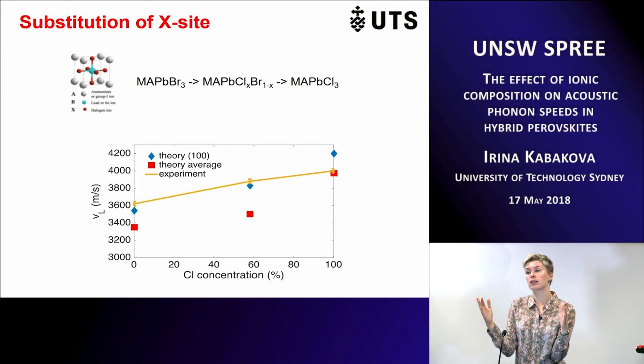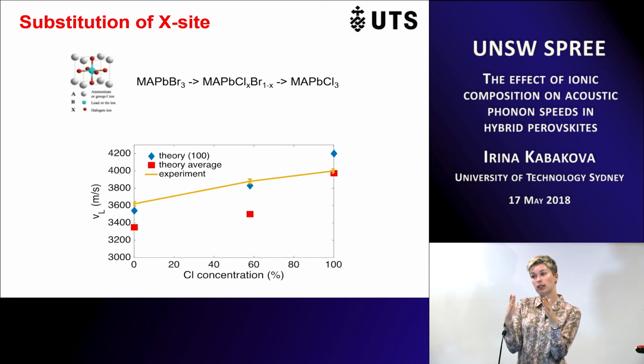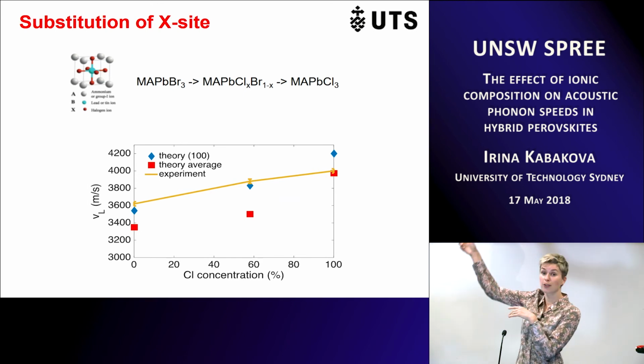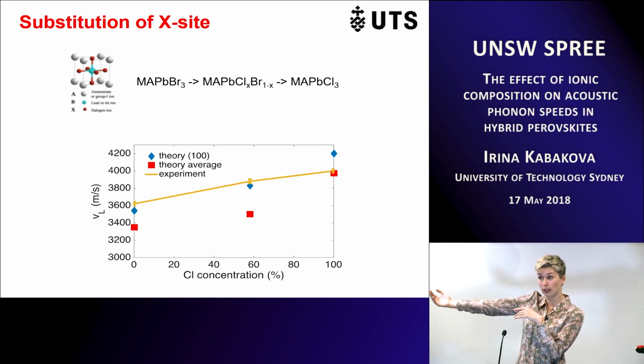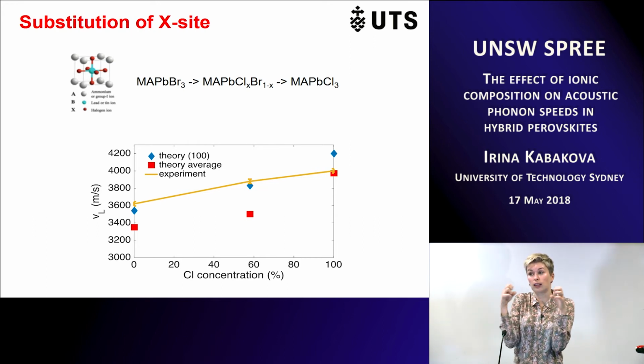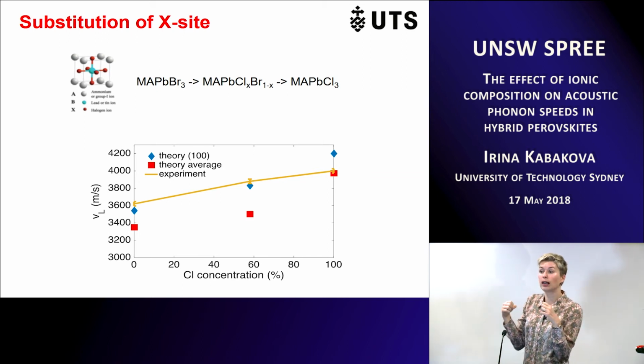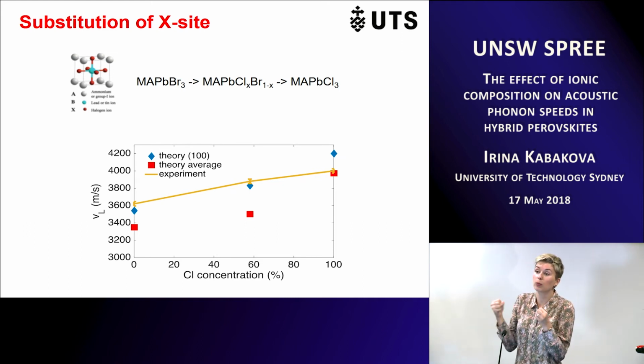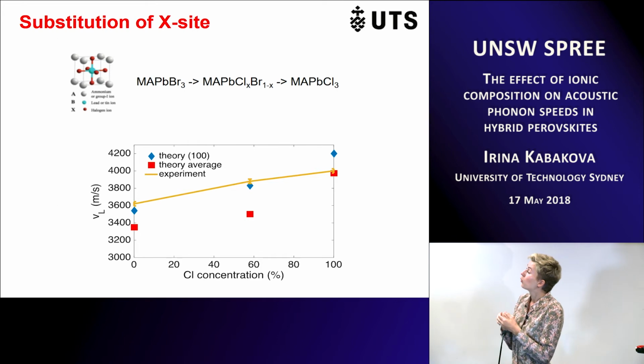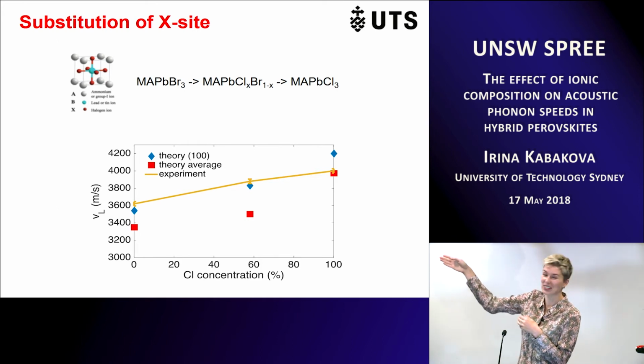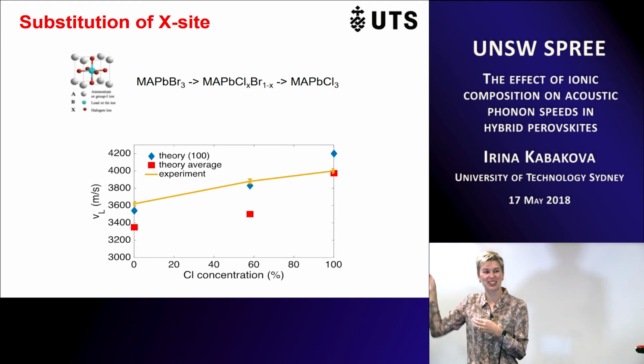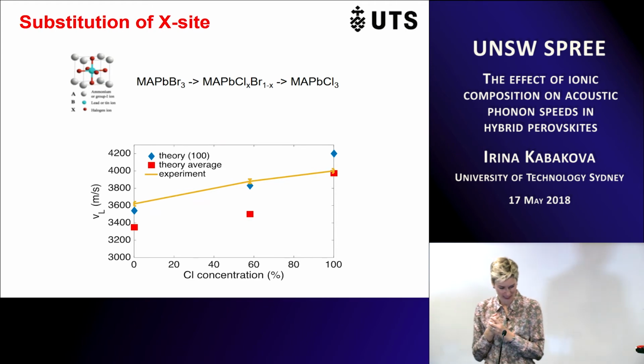So what it means is that the stronger the electronegativity, the smaller the unit cell for chloride, the larger the acoustic speed and the larger the elasticity. It seems that the lattice is more compact and everything is tight and closer together, and electrostatically it's a more stable structure. So good news that the mixture came somewhere in between. That's where we expected it, and that's where we got it.